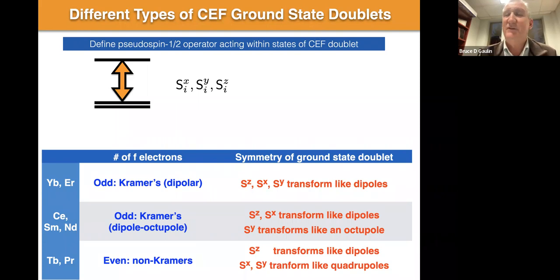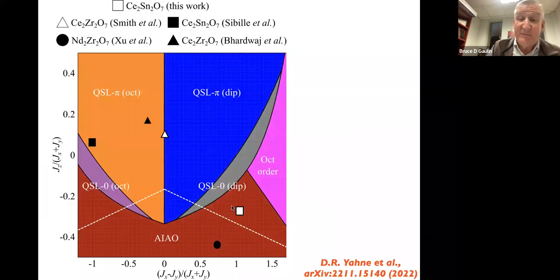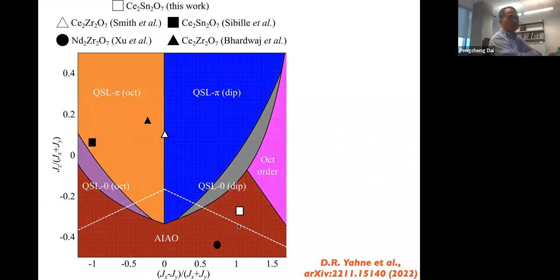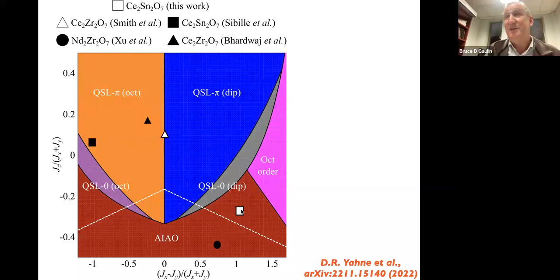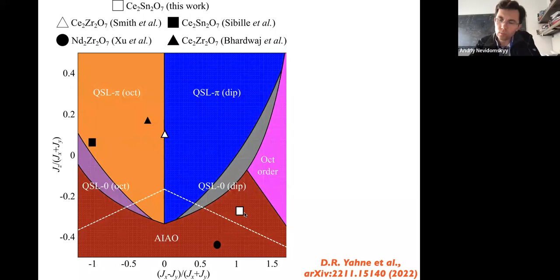But I think that disagreement kind of misses, in some ways, the main point. And the main point was, the measurement at high Q doesn't really give us any more information on the microscopic Hamiltonian, anyway. I went through that pretty quickly, but if I go back to where our analysis places cerium stannate, this has nothing to do with the diffuse scattering. This is really just a measure of the heat capacity. This is just a description of the high temperature tail of the heat capacity and the temperature dependence of the magnetic susceptibility and the low Q diffuse scattering.